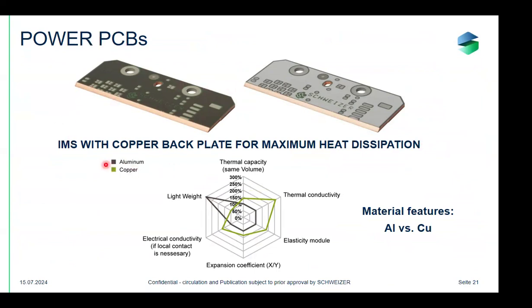So the IMS board is a copper-backed board. Typically, if you talk about IMS, most of the PCB manufacturers are using aluminum-backed IMS boards because they are cheaper. We are using copper-backed IMS boards for two reasons. The one reason is compatibility with our processes inside, and the ability to bring special surfaces onto the top, which is not so easy with an aluminum back. But there is another reason as well. The material of the copper has got several advantages. So the only disadvantage is that it has more weight.